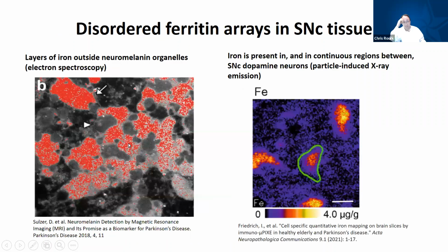organelles. More recently, electron spectroscopy was used to identify iron in layers outside of neuromelanin organelles. Most of the iron in the SNC is stored in ferritin. So this is a good indication that there are layers of ferritin outside of these neuromelanin organelles. This particle-induced X-ray imaging also shows iron between large dopamine neurons in the SNC. So this is an indication that there's iron between those large dopamine neurons.